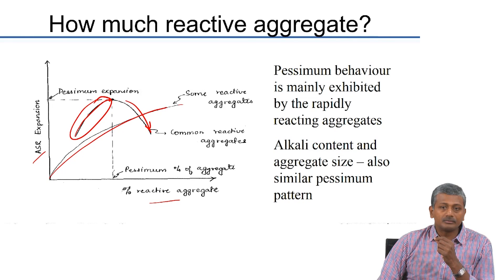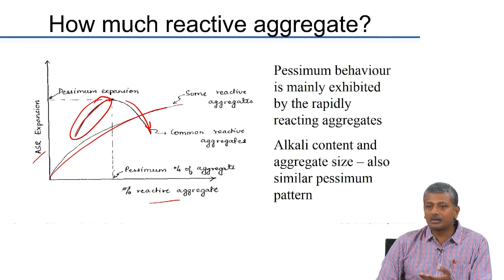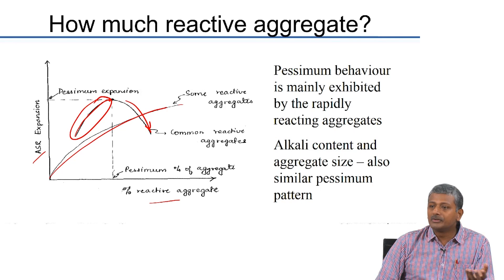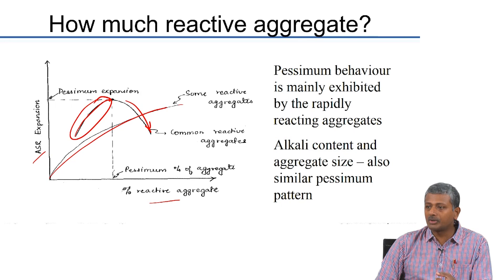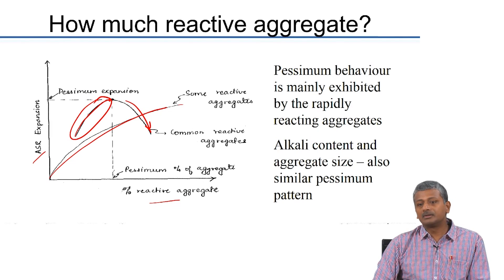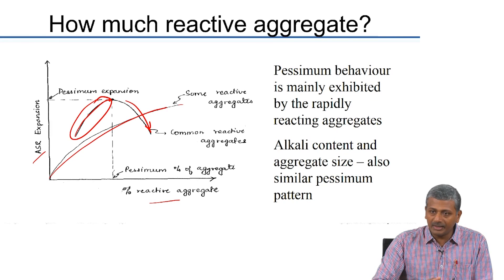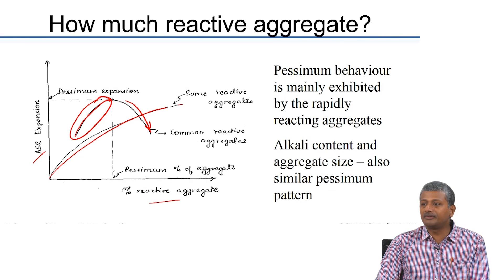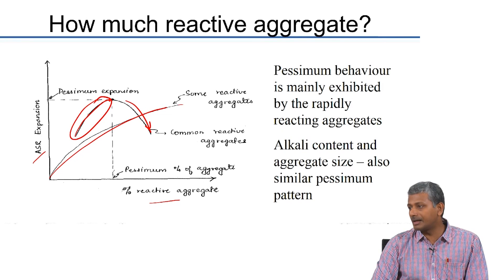Similarly, if you use very small sized aggregate, mineral admixtures which are rich in reactive silica can be thought of as very minute-sized reactive aggregate. But in that case we do not see expansions because the surface area is extremely high, the alkali content is not large enough to create the gel formation needed for expansion, and the unreacted glassy structure of silica in pozzolanic materials traps the alkalis and prevents their association with the silica-formed gel. So there are advantages of using SCMs in alkali silica reactivity — you are first preventing the alkalis from reaching the reactive silica, and secondly the high surface area of pozzolanic particles prevents the alkali from engaging in gel-forming reactions.